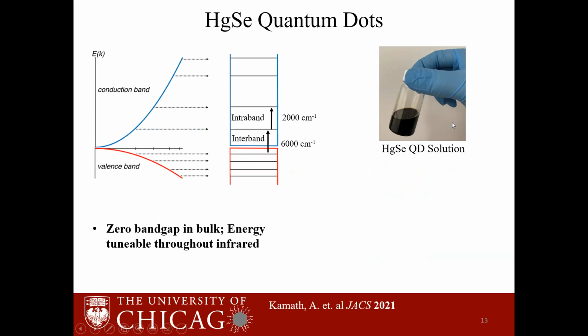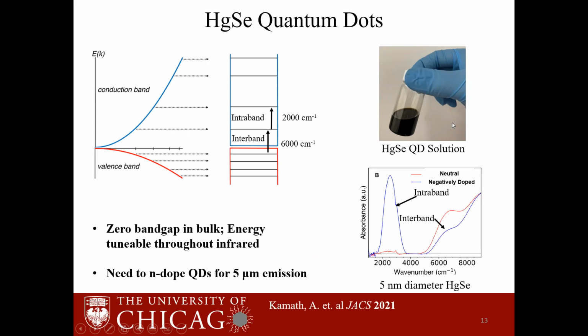The mercury selenide is a semiconductor which has a zero band gap in the bulk. But as we make a quantum dot, we get the band gap to span throughout the infrared region. But as we make a quantum dot, we also get discrete states within the conduction band. And the transitions between these discrete states are called intraband transitions. Intraband transitions are superior emitters to interband transitions because the hole density of states is much less than for the interband transitions. So in order to make mercury selenide quantum dots, where the intraband transition lies in the mid-infrared, which is 5 microns or 2000 wave numbers, we have synthesized mercury selenide quantum dots with a diameter of around 5